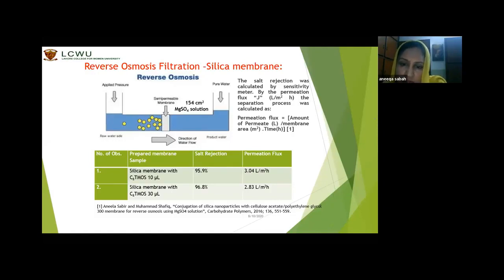It requires almost a long time, so this was actually the deficiency, and we are trying again to improve this filtration. Of course, the filtration was good, the rejection was good, almost 96% of the salt was rejected using this osmosis process and the silica membrane we prepared in the lab, and we have already published this result.